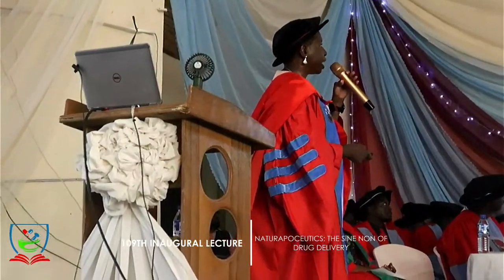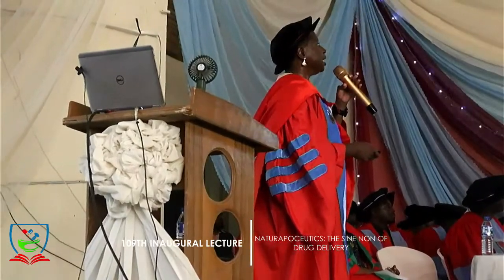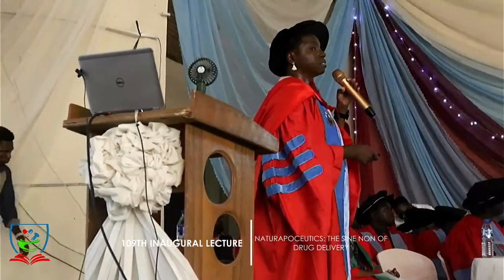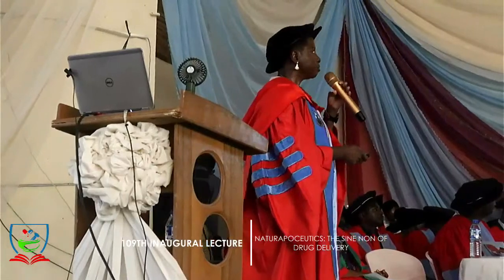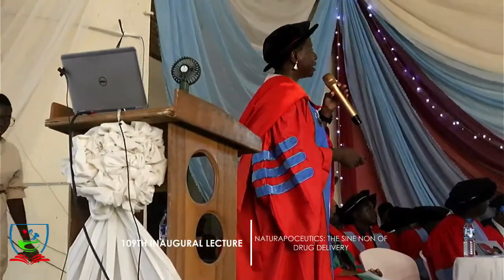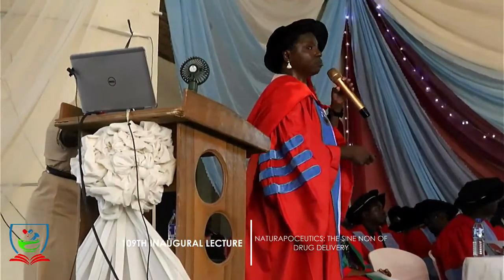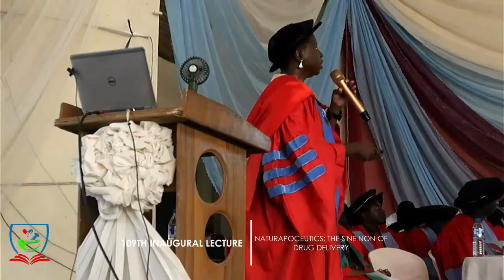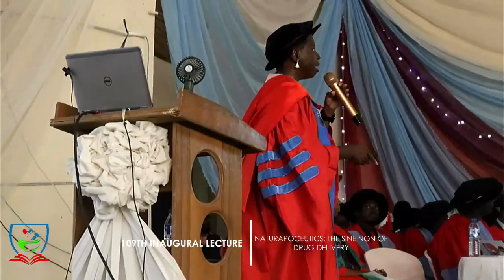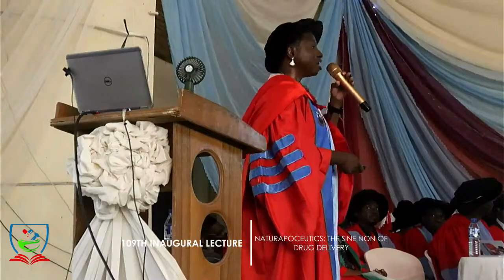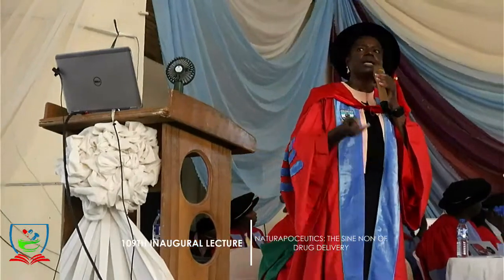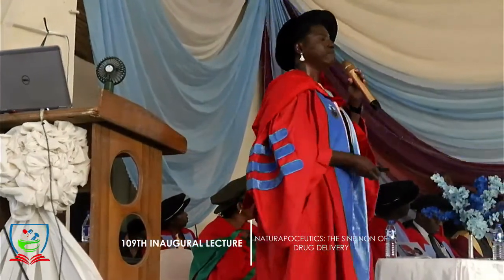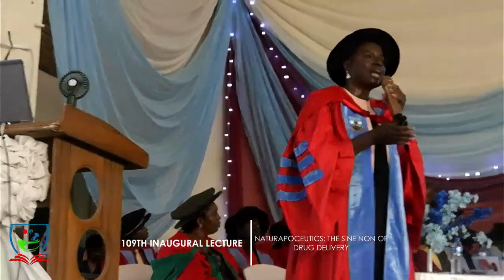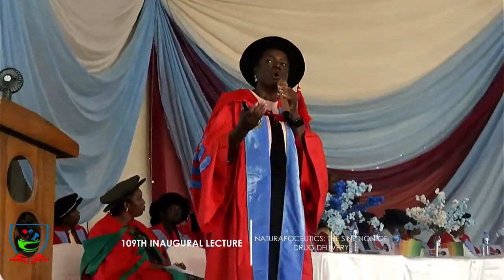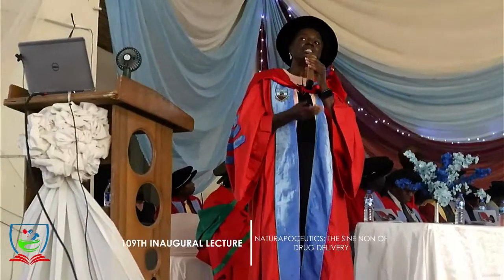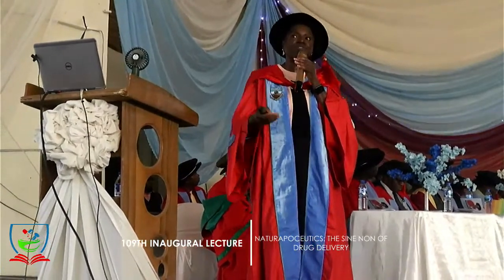So when you have the IPEC plus locust bean gum, it gave us, yes, locust bean gum added some color to it. And then remember we had this burst release here that we were not happy with. By the time we added locust bean gum, we had this. You can see that the formulation is almost a straight line. This is our desire. Now, when it is a straight line graph like this, it means that it's a zero order release, showing that it's releasing the drug at a constant rate over time.